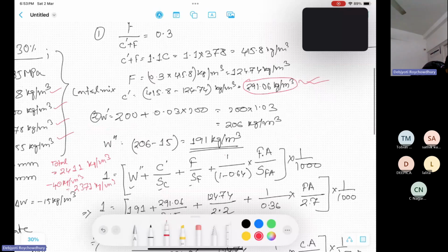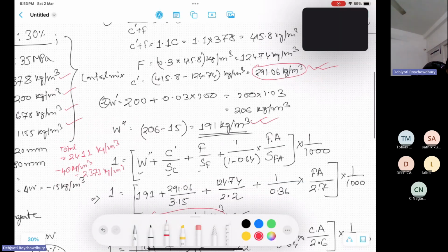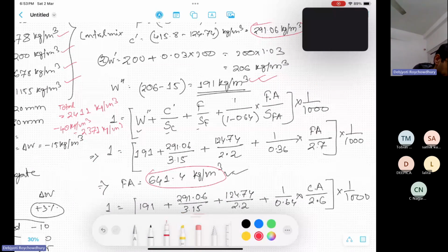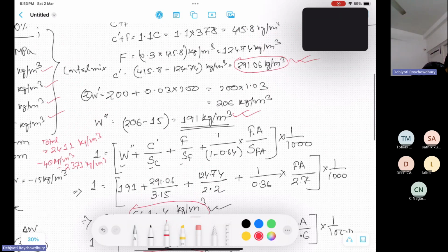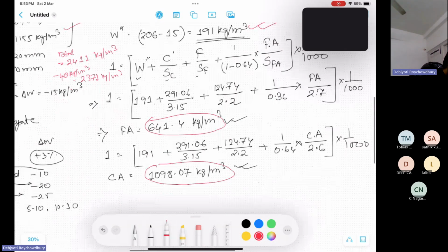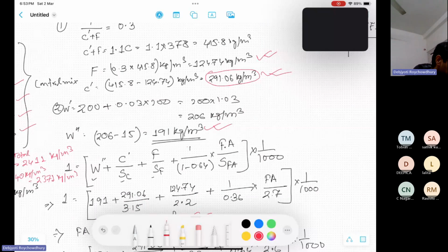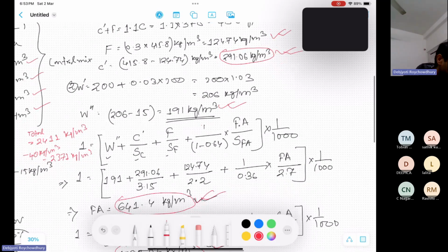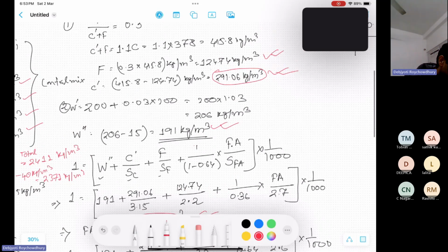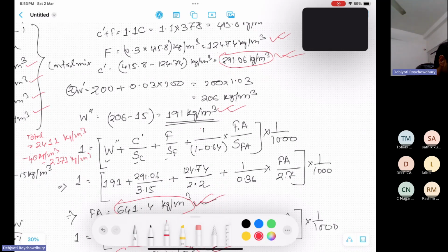So we have this cement content, this is the water content, this is the fly ash content, because fly ash is added here, so fly ash should be included in the calculation. Then the fine aggregate content and coarse aggregate content. So fly ash content 124.7 plus cement content 291.06. This 124.7 is fly ash content, 291.06 is the new cement content.